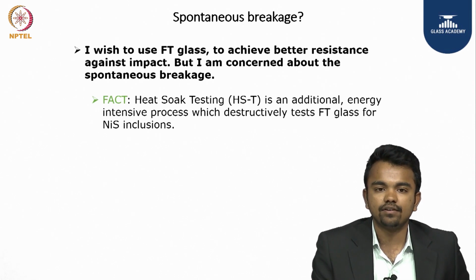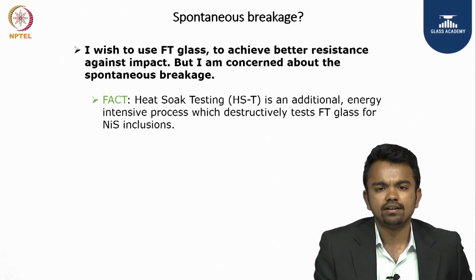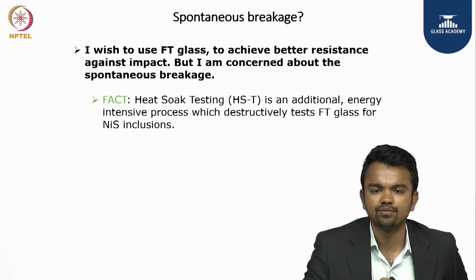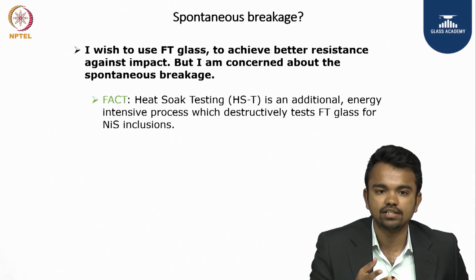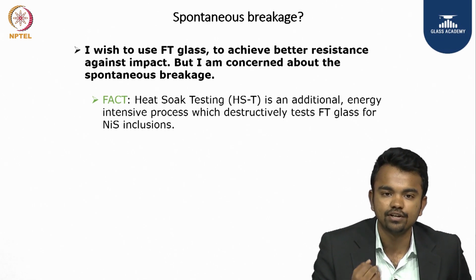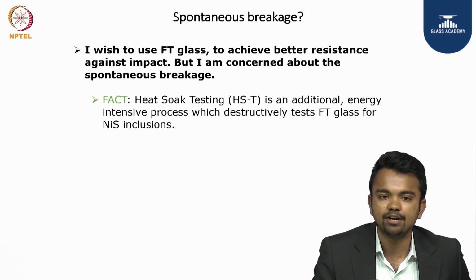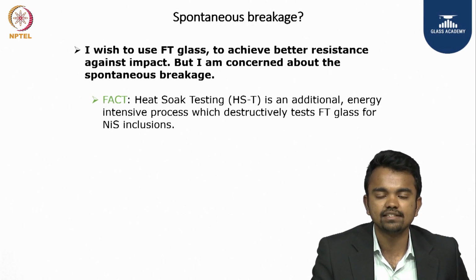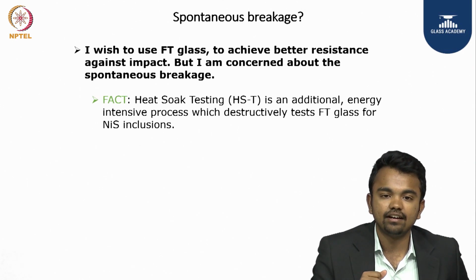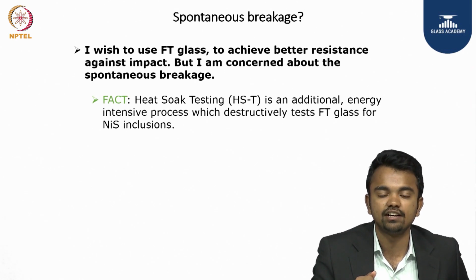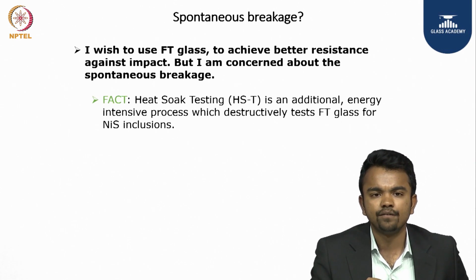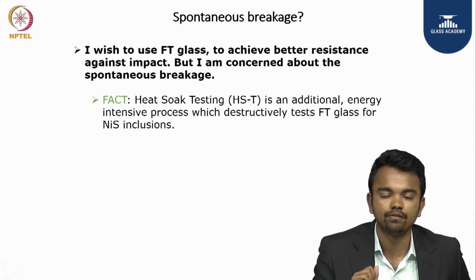To avoid this, there is a separate test called a heat soak test. This is an additional, energy intensive process which tests the glass destructively. The glass panels, after being cut and processed as per your design, and after being fully toughened, are subjected to high temperature in an oven of their own. The nickel sulfide inclusions which may be there in the fully toughened glass are activated in this oven itself so that they do not show up later. The glass with the inclusion breaks within the oven so that it does not even reach you. So this is a process of destructive testing which involves a considerable amount of energy and time on the same panel which was fully toughened.